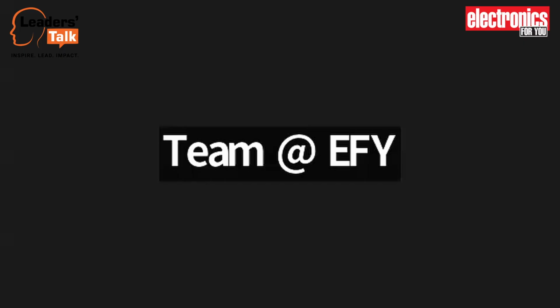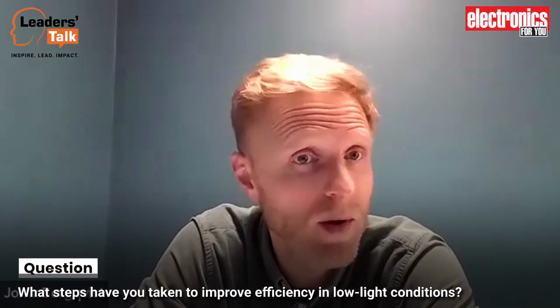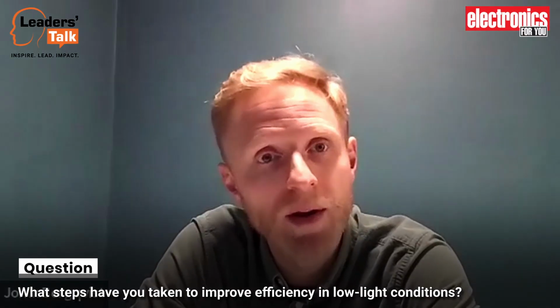Yeah. Focus has been very much to get our product out on the market, and we're working with organic solar cells. And today the active layer is based on a conjugated polymer that's mixed with a small carbon molecule called fullerenes. It's like small carbon footballs with a functional tail on it to make sure you can dissolve them. And this is allowing for a good performance, but what we are also working on now within our R&D team is to exchange these fullerenes for another type of small molecules, and there we will hopefully be able to double the power conversion efficiency of our solar cells, basically by changing a few of the components in the active layer of the solar cells. These are called non-fullerene acceptors in the academic field, and this is of course also where we're trying to push to improve the power conversion efficiency.